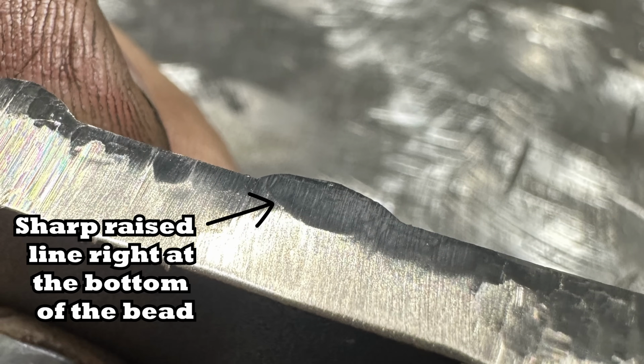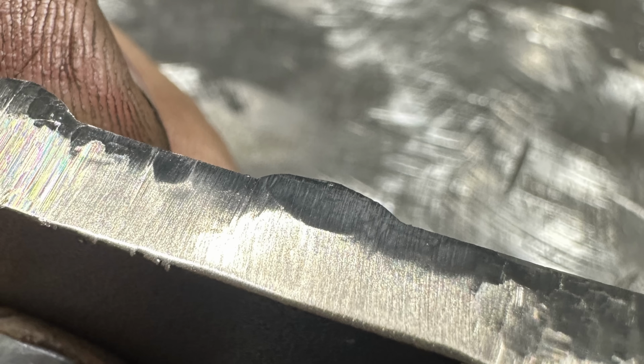So I looked at this up close in person and in this picture as well, and I'm 99% certain that on at least the left side of that bead, that's a crack there. I sat and polished this multiple times, and there always seemed to be like a raised, distinguishable line there. It didn't blend in, and I'm pretty sure it cracked, and that would go along with the pinging I heard as one of the welds was cooling, or at least this one, I believe, is what was causing the pinging as it was splitting off the base material.